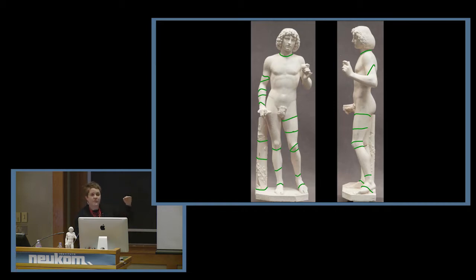So we didn't want to, in other words, the thickness of the adhesive was important. We had an uneven number of breaks on each leg. So we have 1, 2, 3, 4, 5, 6 on one leg and only 3 on the other. So if you're adding dimension from an adhesive, you still need to add up to the torso at the top. So this was a really important characteristic of an adhesive to us. We wanted a strong adhesive, but we also wanted a very thin adhesive.